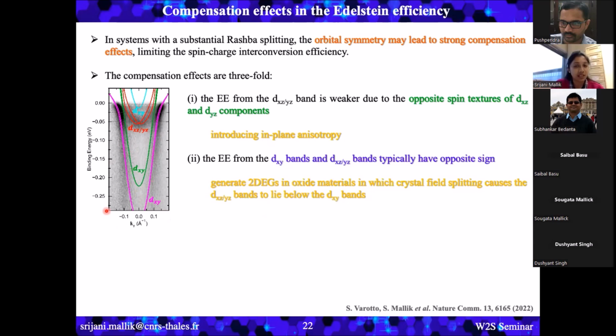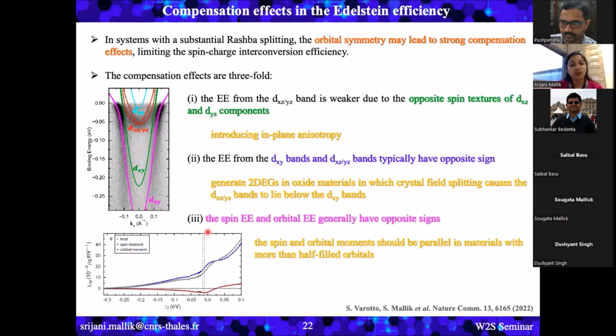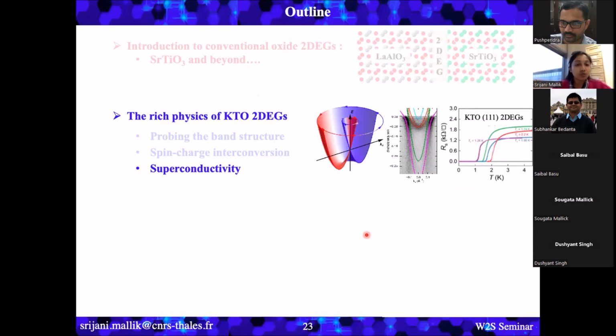And the last one is we found that the spin Edelstein and the orbital Edelstein generally have opposite signs. So we have to choose some material to generate the 2DEG where the spin and orbital moment should be parallel. So we have to choose something with more than half-filled orbitals, basically. So with this, I come to the last part of my talk, which is the superconductivity in KTaO3 2DEG.